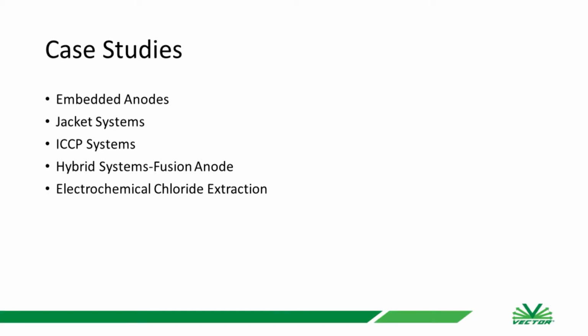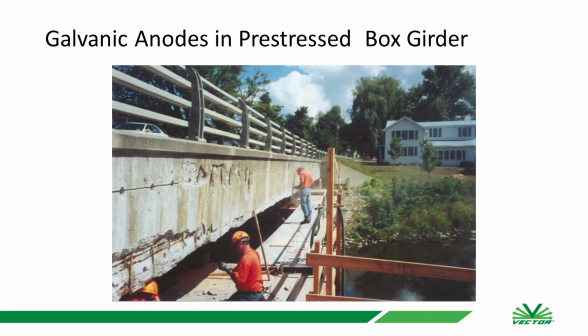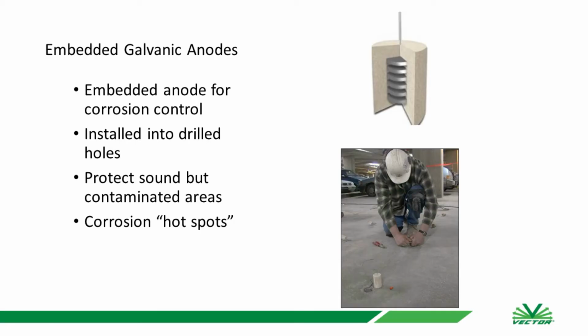A couple case studies and where we've used some of these different galvanic and impressed current cathodic protection solutions. This is some of the galvanic anodes in a pre-stressed box girder, where obviously they had some drainage issues. I believe that really what was happening is water was just coming down and pretty much eating away the face of that girder. And this was, I believe, in upstate New York, where they were trying to get another about 15 to 20 years out of this bridge, because if they didn't, I think the detour was about 25 miles, which would have been really crappy for this guy right here. So our solution for them and to help them out was our drilled in galvanic anodes.